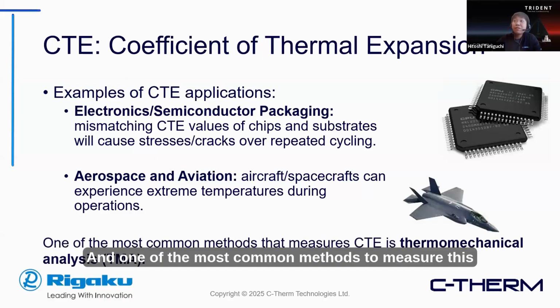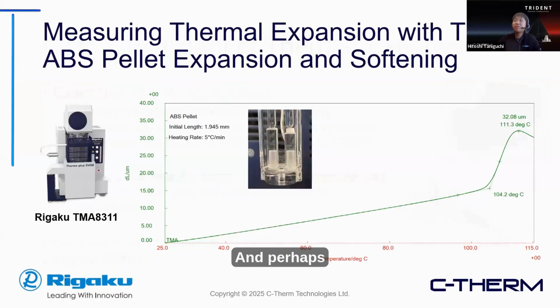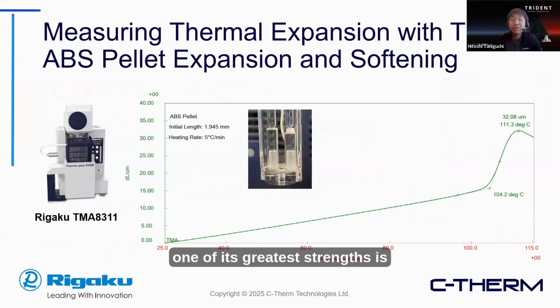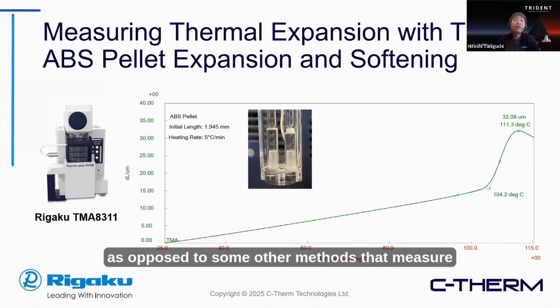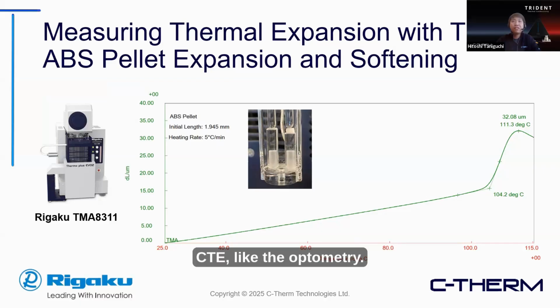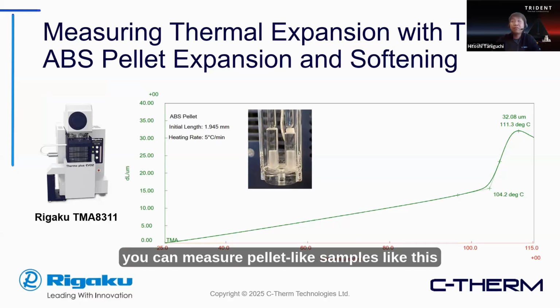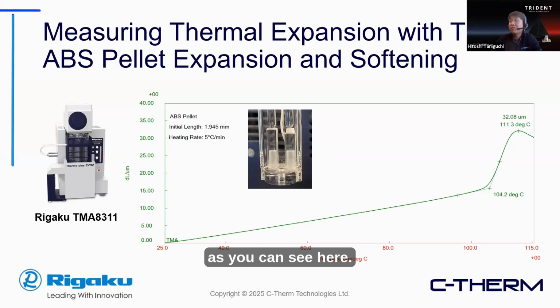And one of the most common methods to measure this property is thermomechanical analysis, or TMA. Perhaps one of its greatest strengths is how flexible it is when it comes to sample preparation, as opposed to some other methods that measure CTE, like dilatometry. Especially with Rigaku's TMA 8311, you can measure pellet-like samples like this one by using a stage method, as you can see here. So even though its thickness is quite small, about 2 millimeters, we were able to measure its thermal expansion, as you can see here.